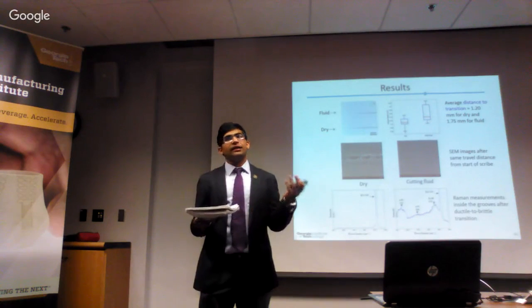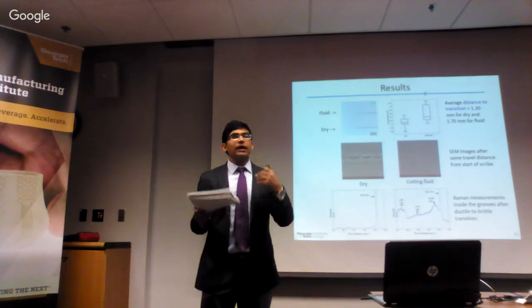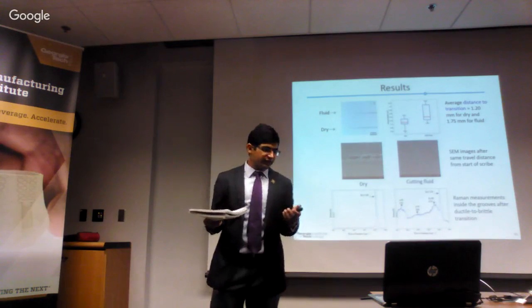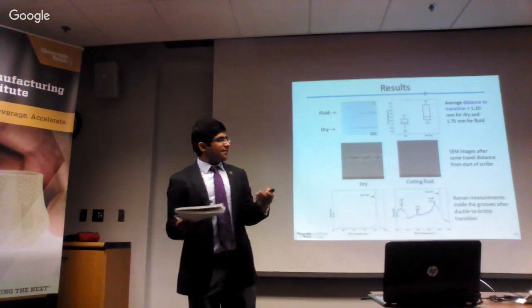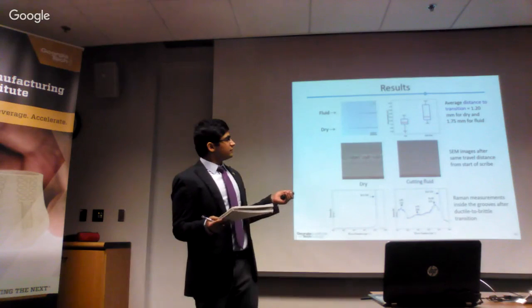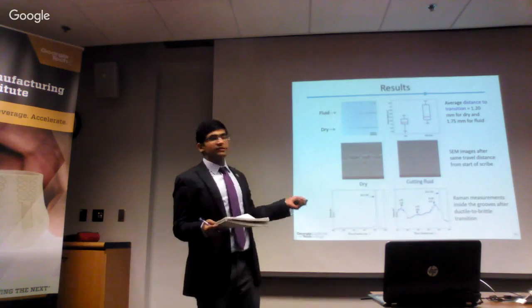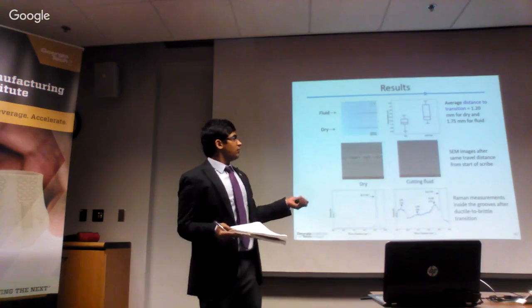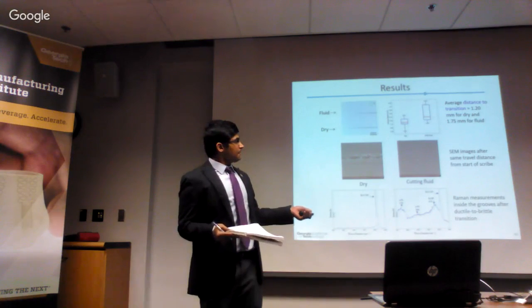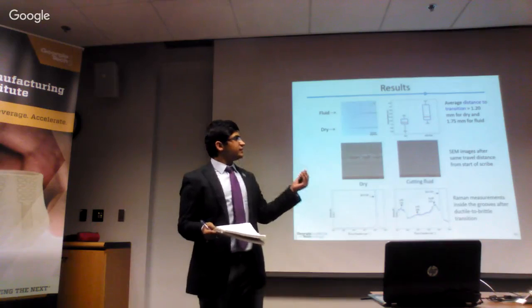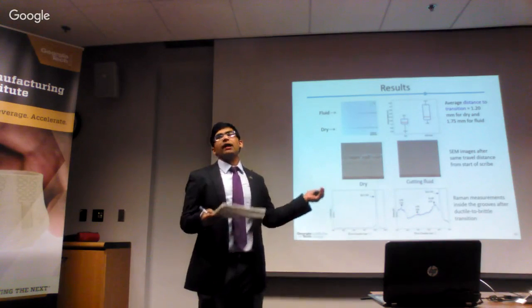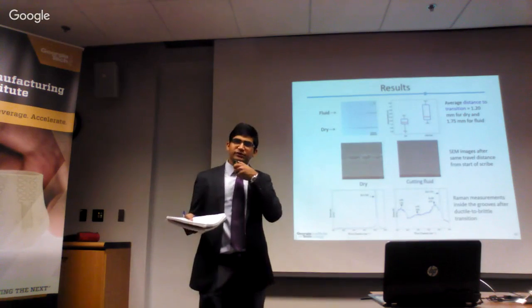No, they're identical. So my hypothesis is the material is getting changed, because if we see the surface at constant travel distance after the start of the scribe, or if we see the Raman spectra as well, we see there is more softening or ductile mode, and also the Vickers hardness indentation which you're seeing.